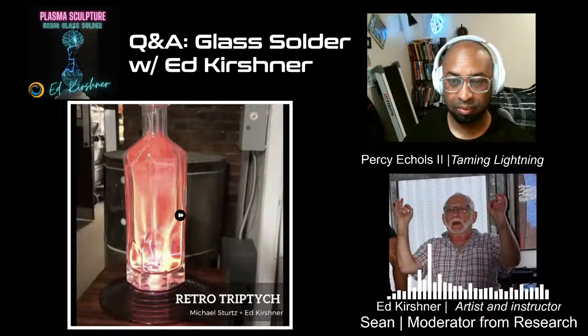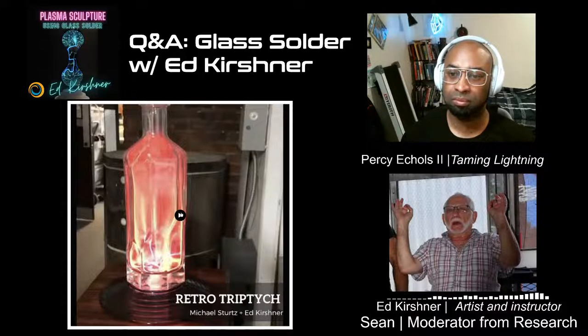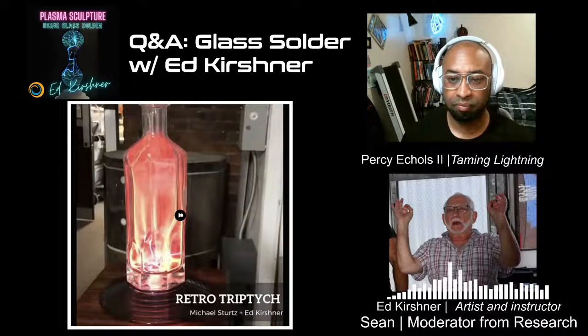Remember when we were in Sweden, there was that guy from, I think, Finland, a real glass expert who made that bio glass. He said, I think what's happening is that most manufactured glasses are coated. They put special coats on it for various reasons, to keep it from scratching when shipping. He said, if you fire it, you may be oxidizing it, and if you oxidize it, even though you don't see it, it becomes conductive. I tested it when I got back from Sweden, and lo and behold, he was right.